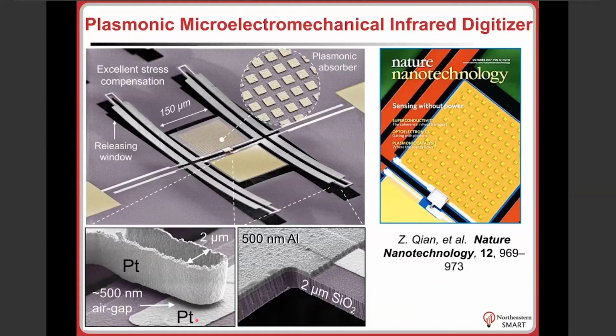You can see here a zoom in of the actual contact tip. Here you see the bowl-shaped tip that I described before. And here there is a tiny air gap. In this particular device it is in the order of 500 nanometers that separates the two contacts. This is a really critical feature, because as you can imagine, controlling this gap with the fabrication process is quite important to have a stable detection threshold for these kinds of switches. And you can see that this in situ mechanism that we integrated in the design of the structure is really effective in achieving that.